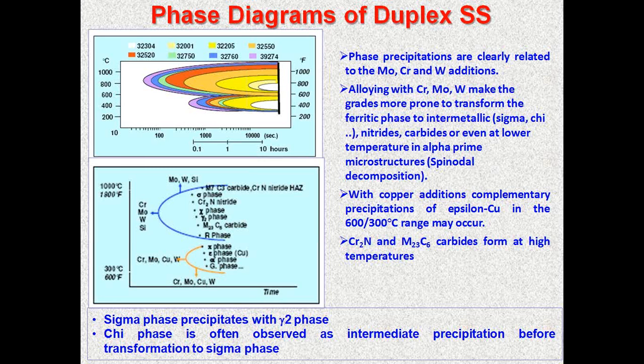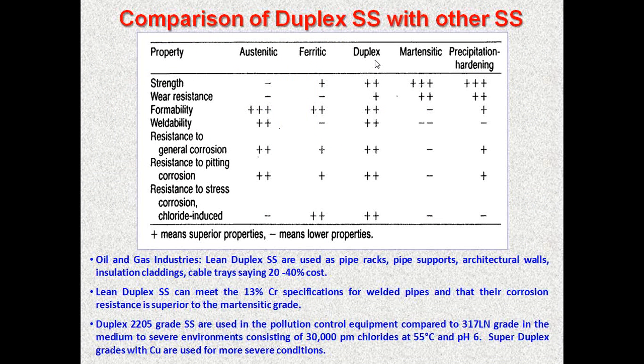And if you compare, if you use it as a wrought alloy, you see austenitic, ferritic, duplex, martensitic, and precipitation hardening. With respect to all these properties, strength, wear resistance, formability, weldability, resistance to general corrosion, resistance to pitting corrosion, resistance to stress corrosion cracking, you can see that compared to austenitic, ferritic, martensitic, and precipitation hardening, duplex is meeting almost all the requirements. It is one of the best choices. And that's how it is being used in oil and gas industries, and also used for various other applications, particularly pollution control equipment, where there is a very severe environment consisting of even higher than 30,000 ppm chloride.